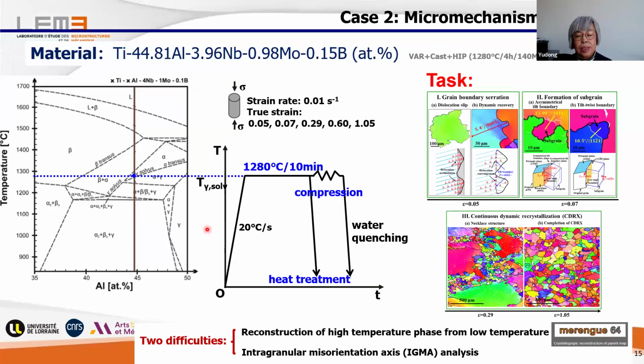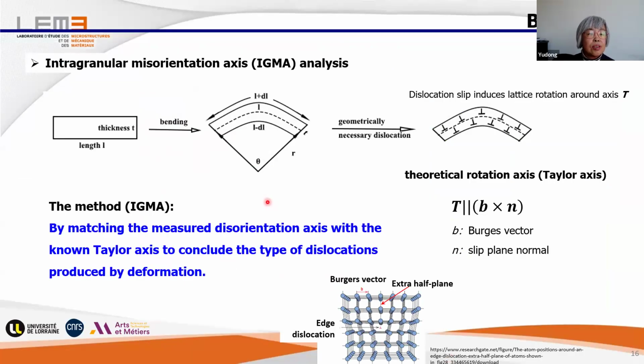Then we have a second problem. We can artificially reconstruct the single alpha phase, but if we do the examination with TEM or with SEM, we cannot examine the dislocation configuration, because in the sample we have, you see, at room temperature we have the beta phase and the gamma phase. Then we use a crystallographic tool: intragranular misorientation axis analysis. This is not invented by us, but we made an application, and so I have to introduce this method a little bit.